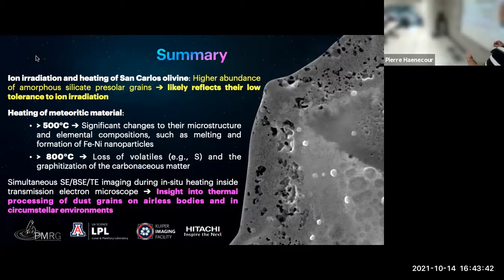So I hope I showed you, in this preliminary data, that simultaneous electron imaging during in-situ heating, inside of either an electron microscope or a transmission electron microscope, is really critical in terms of constraining thermal processing and its effects, both on the surface of an asteroid, but also inside of an asteroid with more long-term, lower temperature heating. We want to constrain what we actually observe from the return sample and compare it to laboratory experiments, and as we get more and more heating experiments, try to really match specific temperatures to specific microstructural compositions that we can see in the sample.